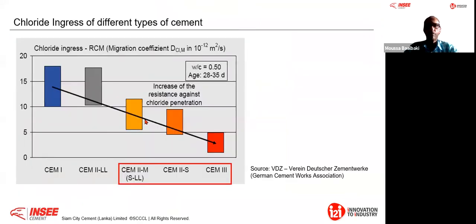And now you see, for example, if you look at the chloride ingress, if you take a CEM I that is an OPC or a limestone cement, in terms of corrosion, when you have high corrosion designed for 100 years, they are similar. But as soon as you move to Portland composite cement, CEM II/M, mixed composite cement or slag cement, up to 35% or above 35%, the CEM III/A or CEM III/B, which we don't have in Sri Lanka yet, you see how the chloride density goes down. That is the beauty of this Portland composite cement. Therefore, you have less diffusion of the chloride.